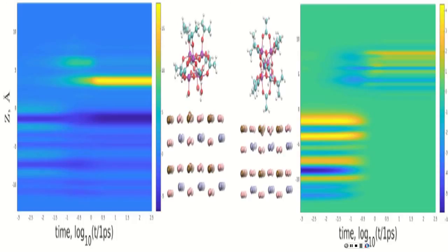But if we allow this structural change by replacing isopropanol with hydroxyl, we start with both electron and hole originally on titanium dioxide, and then the hole stays on the perovskite slab, and the electron jumps to titanium dioxide. So just a little chemical tweaking of the linker makes a drastic change in the quality.